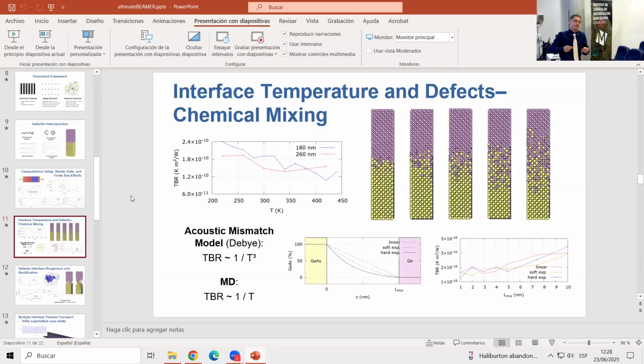So this is just a linear proportionality law: the longer the region where the thermal conductivity is low. Let's imagine that you have a definite very low thermal conductivity in the mixed zone. If you double the length of the mixing zone, you will double the contribution to the TBR. So it's related also to disorder, to local disorder, I guess? I would say yes. I would rather claim that this has to do with disorder rather than any other artifact or physical phenomenon.